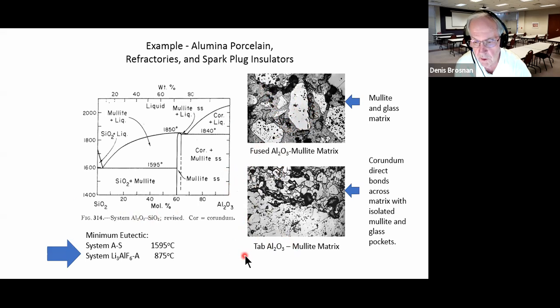A second way to meet about the same chemistry specification is to use tabular alumina. Here's a grain of tabular alumina. You can see the little crystals developed, and what's harder to see at this magnification is direct bonding, but occasionally you'll see direct bonds between corundum and the matrix phase into the fused alumina aggregate. So to make the strongest possible product, we want to have these bonds extending across the matrix between the coarse particles. So we expect glass